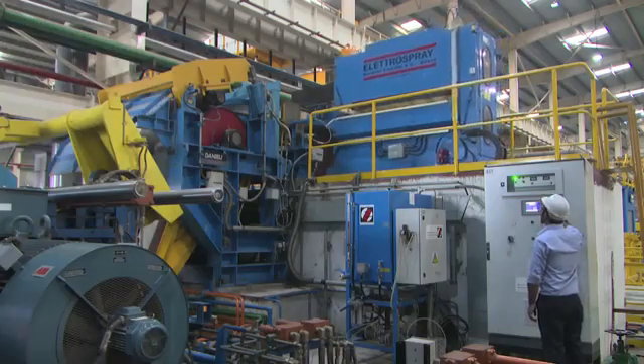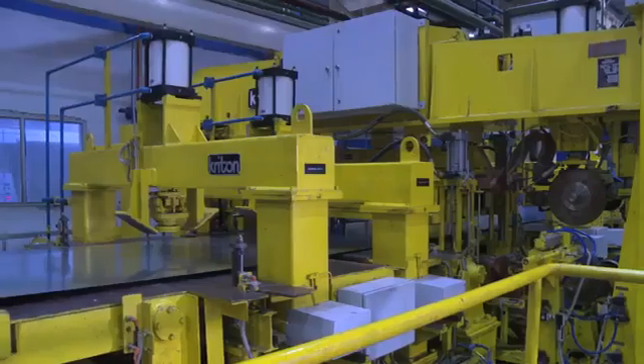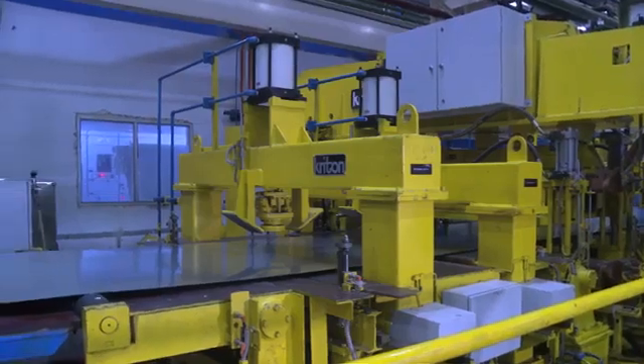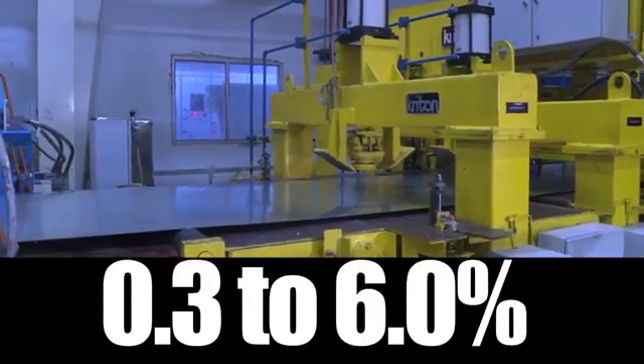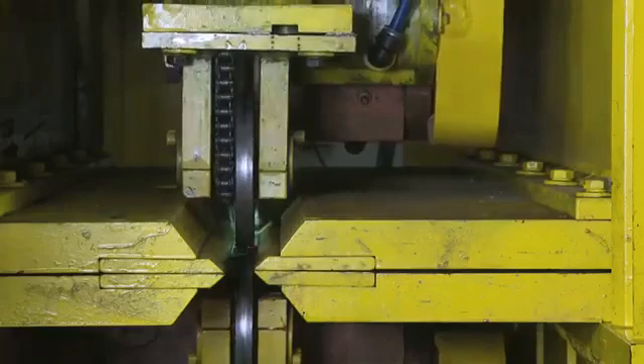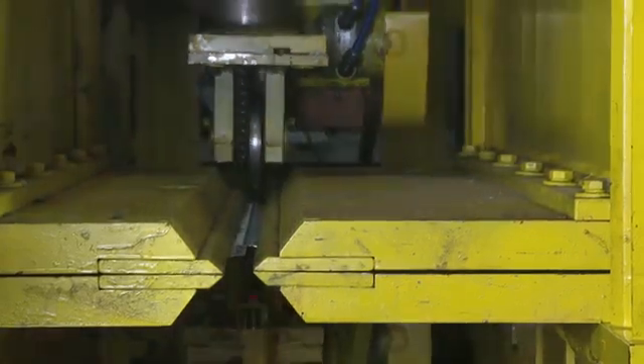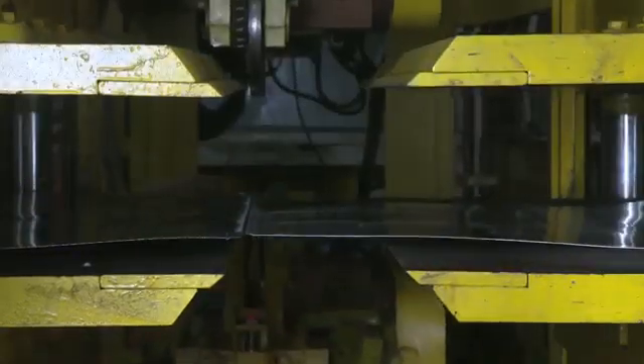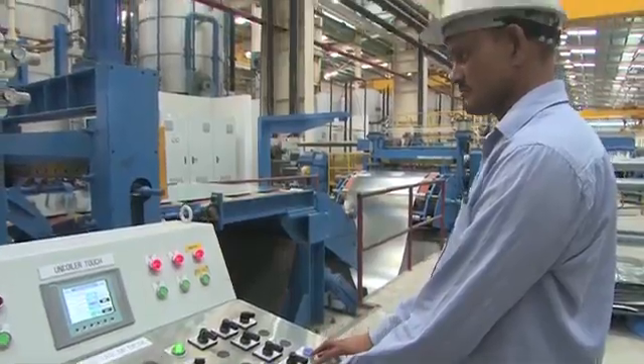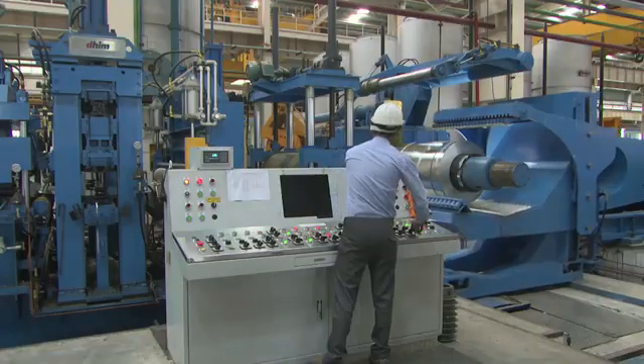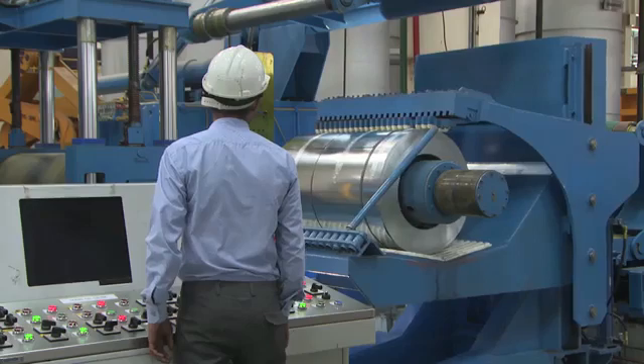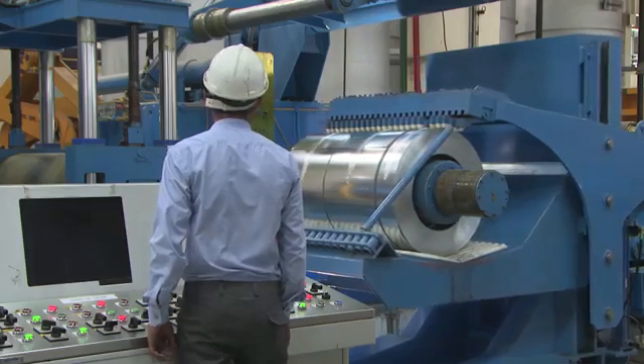The mill is equipped with online tension leveling and an electrostatic oiler. Skin pass elongation can be controlled between 0.3 to 6%. Mill operation is monitored and controlled from a centralized pulpit. After skin passing, the coils are transferred to the CR slitting line, where the coil gets slit as per the client's requirement.